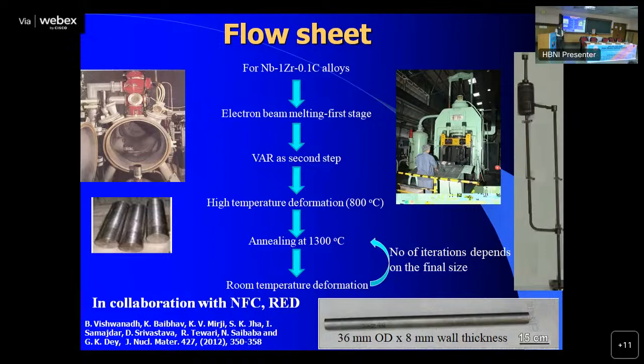So the problem is that niobium-based alloy is extremely prone to oxidation. Niobium will oxidize very quickly, and it's a high temperature alloy, so all processing has to be done at slightly higher temperature. So the problem was to find a temperature regime where the oxidation will not be very large, and you can still deform it. Our research shows that around 800 degrees centigrade, the nature of precipitates is not so bad, and you can do deformation. If you go beyond 800, some of the deleterious phases will start forming, and the material will start cracking. So that is the vital information which came from research, and that was put into the development of this flow sheet.